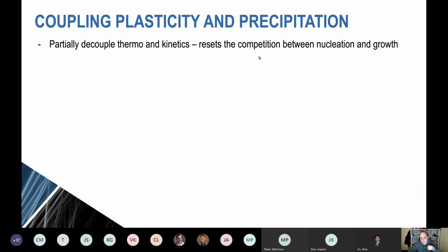By using plasticity to inject vacancies, we're able to partially decouple the thermodynamics and kinetics. Previously, using traditional thermal treatments, we use temperature to control both the thermodynamics and kinetics, and that has some constraints around it. Now, by injecting the vacancies using plasticity, we can partially decouple that. Now, I say partially because, of course, mass transfer depends not only on the presence of the vacancies. Our solute atoms also have to be able to jump into the neighbouring site, and that depends on temperature. So it's only a partial decoupling, but it's a very important decoupling because it allows us to reset a little bit the competition between nucleation and growth. We're able to get a very large amount of nucleation and minimise the amount of growth, and this has some very interesting effects.